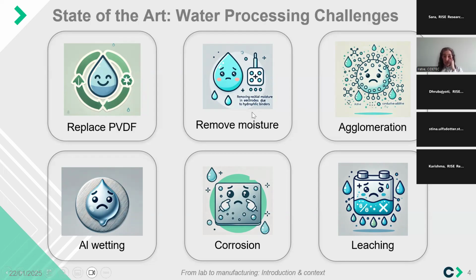Main issue then is that since we are working with water as the solvent media, we have to be more careful of removing any residual moisture trapped in the porous electrode during the drying step, but particularly the mixing steps are the main problems. It's more difficult to avoid agglomeration of the components together, so the electrodes are not as homogeneous as with the standard PVDF in NMP.